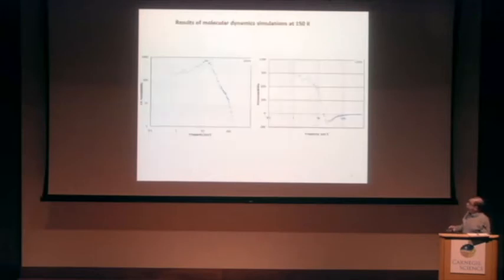We use the supercell of 18 by 18 perovskite unit cells and simulations at about 50 different temperatures in the range between 1,000 and 10 K. And then we calculated the time dependence of the dipole moment of the supercell. And then, using this formula, we calculated the real and imaginary part of electric susceptibility. This is the example of what we have at some particular temperature, 150 degrees. These are the frequency dependencies of real and imaginary part of susceptibility.